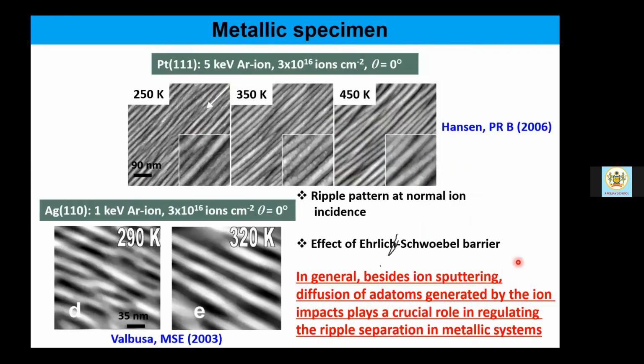Again, wonderfully ordered ripple patterns we get to see here. And this we see for platinum. But the important difference here, in contrast to the previous slides, is that here again, the pattern formation is taking place at elevated temperatures. So in general, besides ion sputtering, diffusion of adatoms at higher temperatures generated by the ion impacts plays a crucial role in regulating the ripple separation in metallic systems. This is very important.